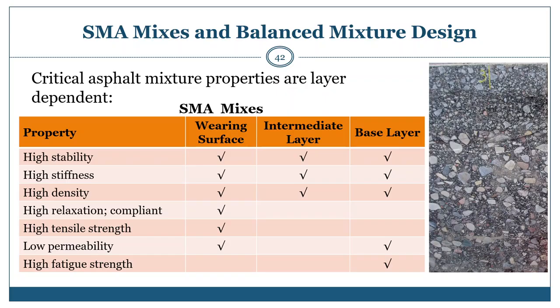SMA mixes are mostly placed as wearing surface courses on high-volume roadways. Based on test findings, it has been found that using SMA mixes as a wearing surface is beneficial over intermediate layers and base layers, resulting in higher stability, higher stiffness, higher density, higher relaxation, higher tensile strength, but lower permeability. It was also observed that use of SMA mixes as a base layer will result in higher fatigue strength, but SMA mixes are typically not used in a base layer.